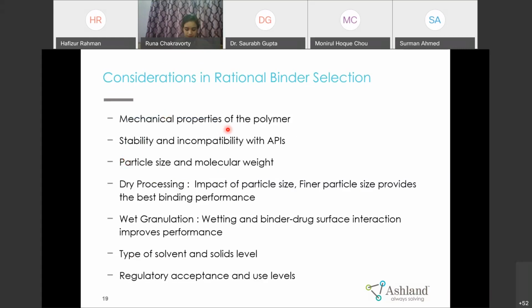One is the mechanical properties of the polymer: whether the polymer is plastic or elastic, how is the plasticity, how is the toughness. Then stability and incompatibility with API, and particle size and molecular weight of the polymer. I will show you in coming slides how particle size and molecular weight impact compactability and product performance. If you are doing dry processing like direct compression or dry granulation, particle size is very important. As finer grades have larger surface area, they are capable of binding tablets more strongly than coarser particle size binders.